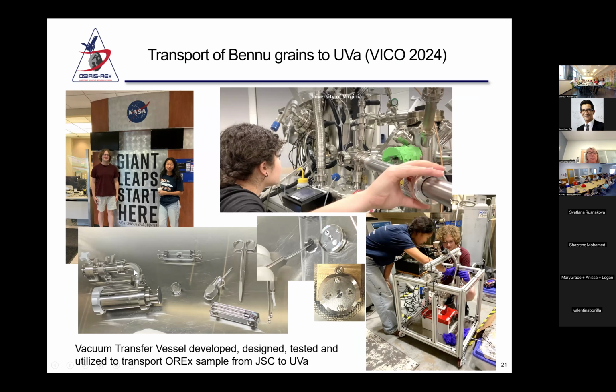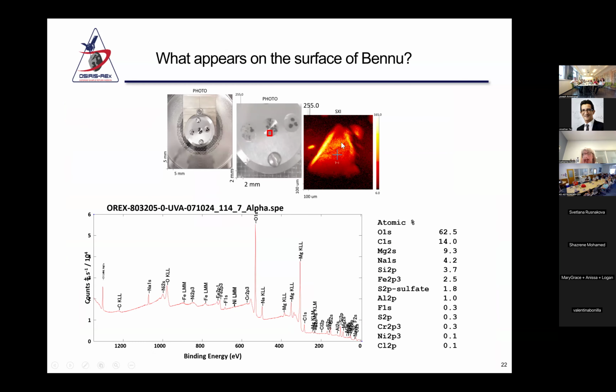So we had developed this little vacuum transfer vessel here on the left-hand side. You see it inside the nitrogen glove box, outgassing here. Our samples were put on top of our sample platen, which was then installed in our sample vacuum vessel. Then this was pumped down on this little cart that Jackson and Annabelle are working on, and brought to UVA. Subsequently, you can see Lianis here putting the samples into our XPS instrument.